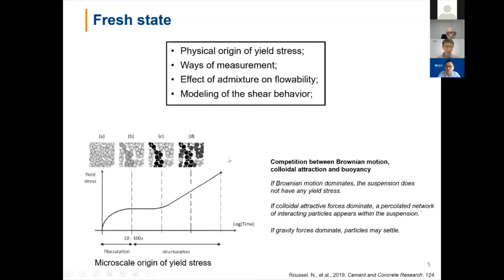For example, for the fresh cement mixture, we already know that the rheology behavior of the fresh mixture is a result of the competition between the Brownian motion of the cement particles, which is the random motion of cement particles in water, and the colloidal attraction between the particles and the buoyancy of the particles in water. If the Brownian motion dominates, we see that the suspension will not have any yield stress. That means the cement particles will not touch each other. They will be away from each other. And this is exactly what we want during the casting and pumping stage. We want the cement to be extremely flowable and pumpable.